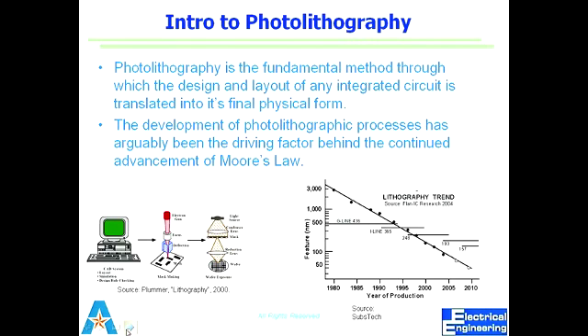trying to have a larger depth of focus is not only driven by the thickness of resist, because we can always come up with a new chemical which is thinner, but there might be several layers. There is topography on the surface of the chip, right? So topography means you have now made different levels of devices which result into the surface which is not planar, which has local planarization. Maybe you can get local planarization, but there are different levels now which are at different height, right? So not just the minimum feature size, depth of focus is also an important factor, and both depend on lambda. We want to push lambda or wavelength down to have minimum feature size, but that also results into depth of focus reducing. So what do we do there?